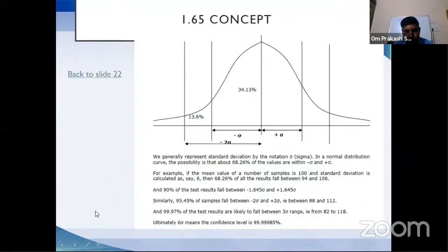Here. This is the concept of 1.65. Here you can see minus sigma to plus sigma. 34.13 is on the lower side, 34.13 on the higher side. Means our more than 90% result will fall in this range, and according to that, the factor is minus 1.645 to plus 1.645. From here, we have selected the 1.65 as a correction factor.